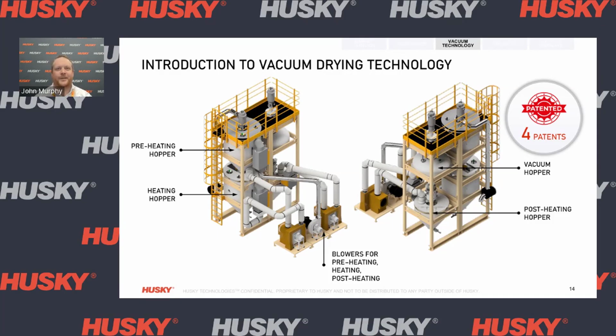So first, as resin enters the system, it begins in the preheating hopper in the top left of the screen, where it is heated to approximately 100 degrees Celsius to remove easy-to-remove surface moisture. Next, the material flows down into the heating hopper, where it undergoes further heating in preparation for vacuum exposure. From there, the material is transferred up to the top right of the screen, which is the vacuum hopper. In the vacuum hopper, the resin is subjected to vacuum conditions. This is effective in drying the material to below 40 ppm, making it ideal for the injection molding process. Finally, material is transferred to the post-heating hopper, where it is heated to the precise temperature required for the injection molding machine.